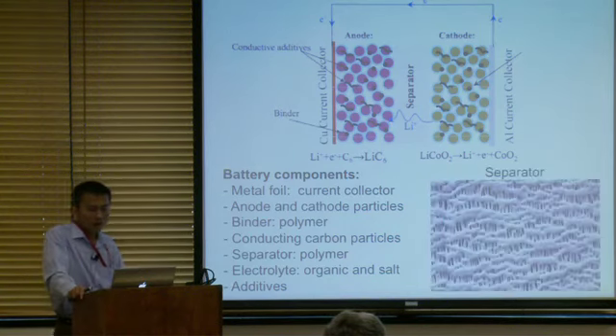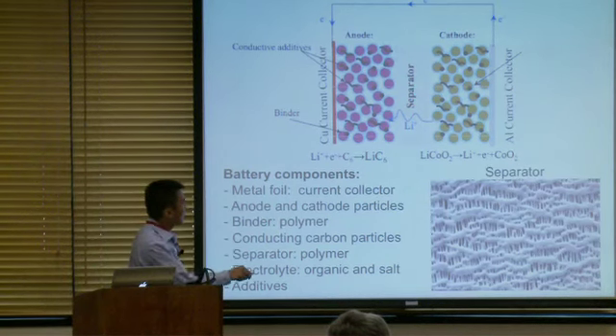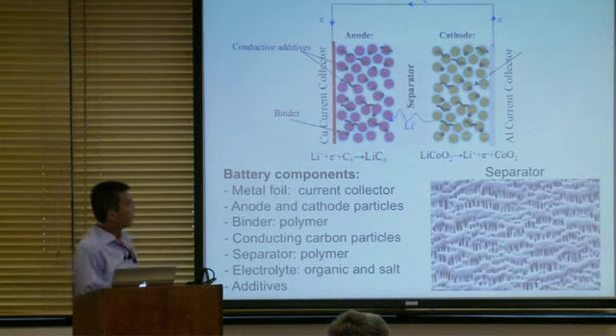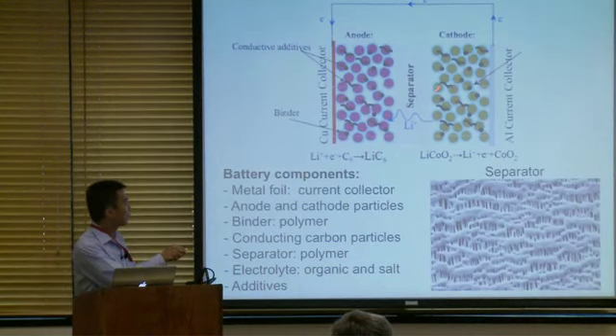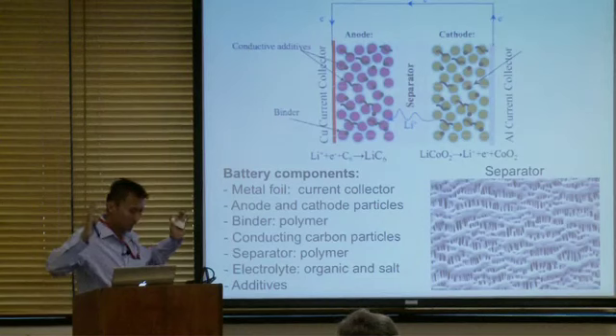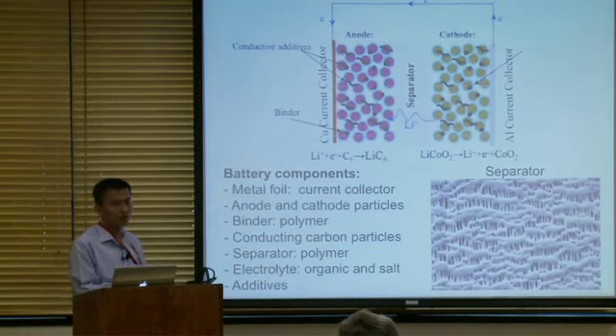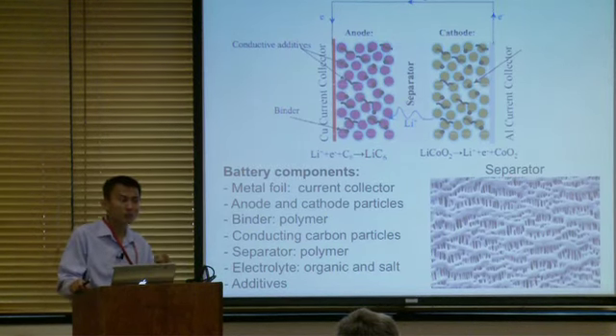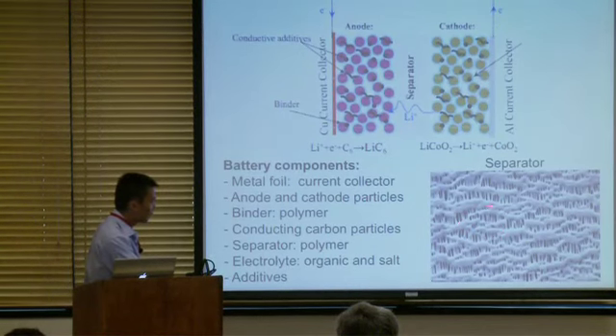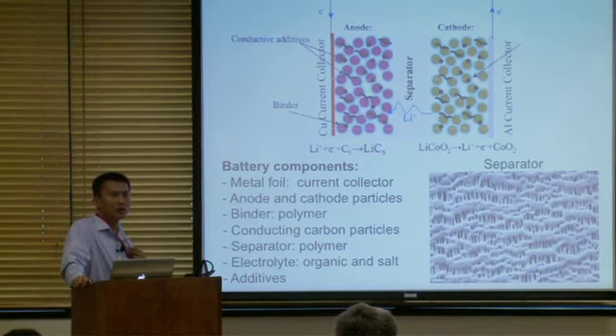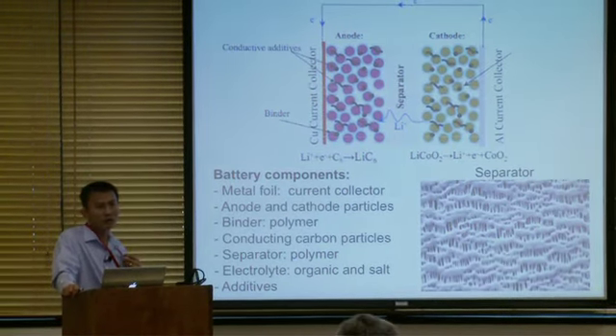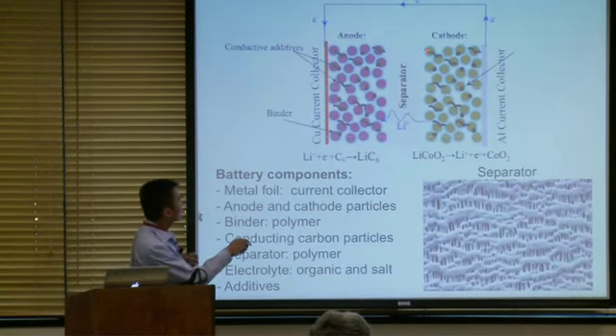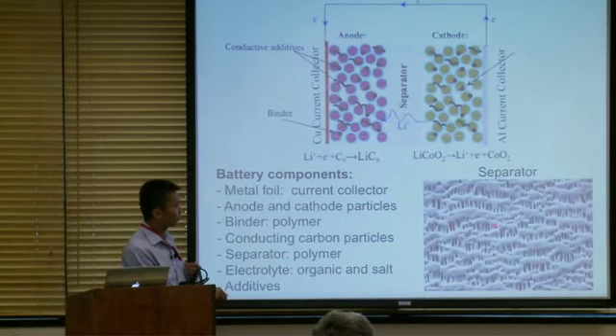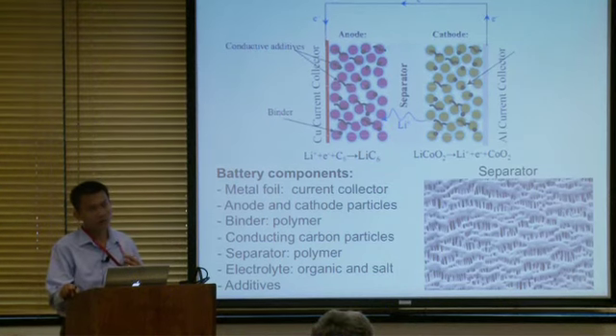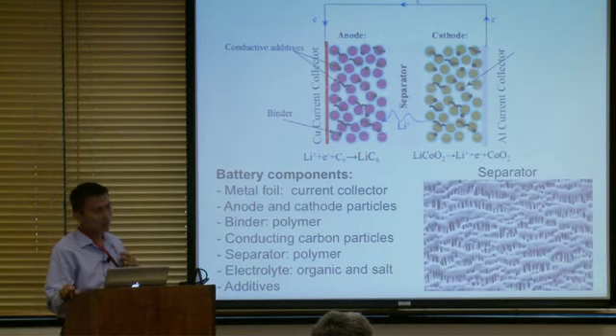They all interplay. Let me mention the battery separator right here. You don't see people talk about this too often. It's a highly porous structure with nanoscale pores, for a lot of liquid to move through. But once you make the battery, you compress the positive and negative electrodes. You don't want them to short. So this separator, typically made of polymer, needs to be very strong and very well made. You cannot have a bigger hole like this right here. If you have that, you will have shorting. It's extremely important. LG Chem, a company in Korea, developed a new type of separator simply by putting a ceramic coating, a hard inorganic coating, onto this organic polymer separator. You can increase the safety dramatically for mechanical strength reasons. There's a lot of invention in that area.